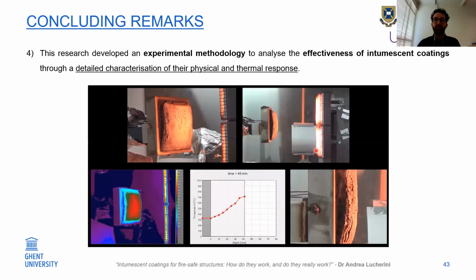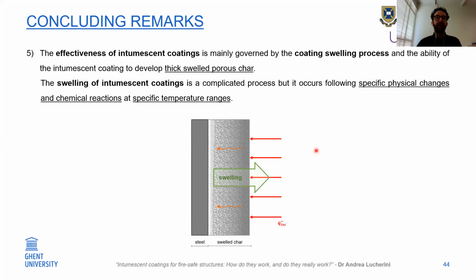influence their effectiveness. So first, I showed you that by collecting a lot of information and having very well-defined thermal boundary conditions, I developed an experimental methodology to analyze the effectiveness of intumescent coatings through a detailed characterization of their physical and thermal response. And also, the effectiveness of intumescent coating is mainly governed by the coating swelling process and their ability to develop a thick swollen porous char.